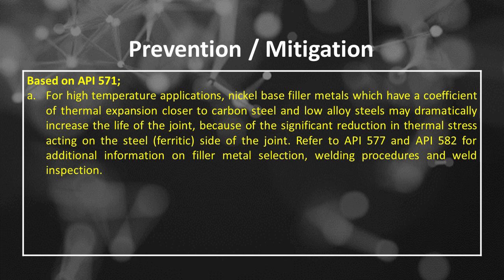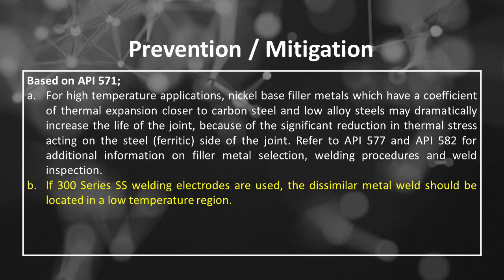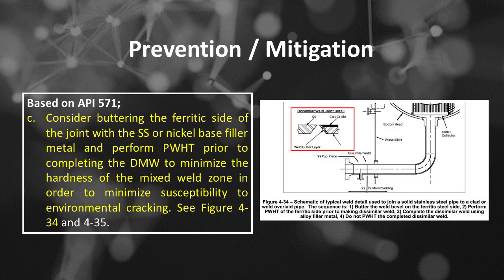The second is if 300 series SS welding electrodes are used, the dissimilar metal weld should be located in a low-temperature region. The third is consider buttering the ferritic side of the joint with the SS or nickel-based filler metal and perform PWHT prior to completing the DMW to minimize the hardness of the mixed weld zone in order to minimize susceptibility to environmental cracking.